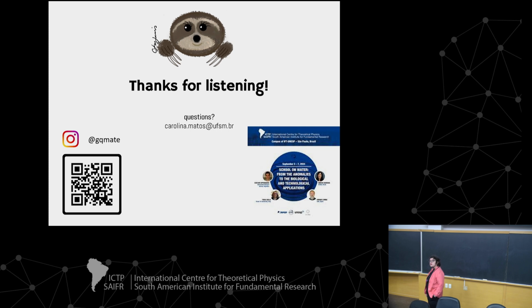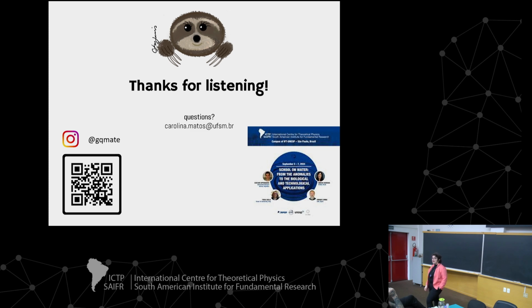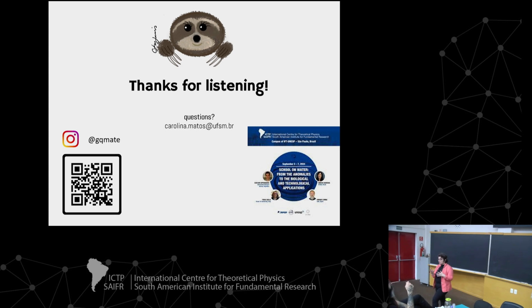Can we assess a mean distance, an average distance from the experimental point of view? Yes. We use BET surface area measurement, normally using nitrogen gas. We know the amount of molecules we insert in the system, and we can calculate using pressures and some mathematical artifices, and we can discover the size of the pores. We have a histogram from the smaller to the higher median about these values. The surface area, the mean distances and other characteristics using this technique.